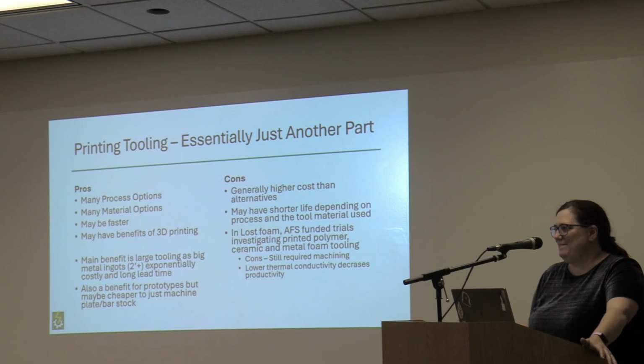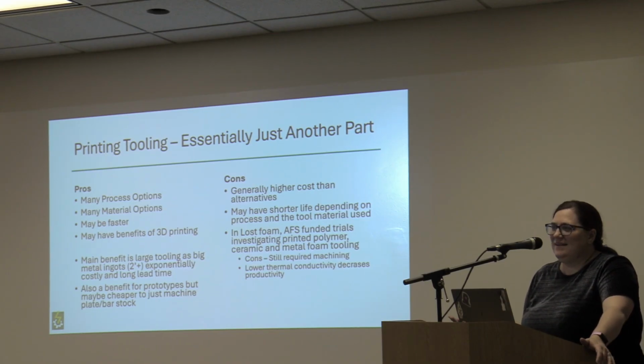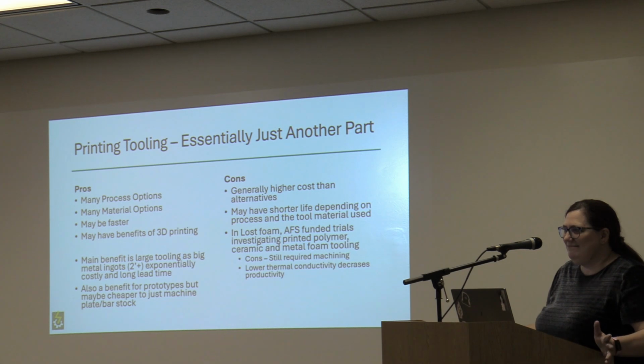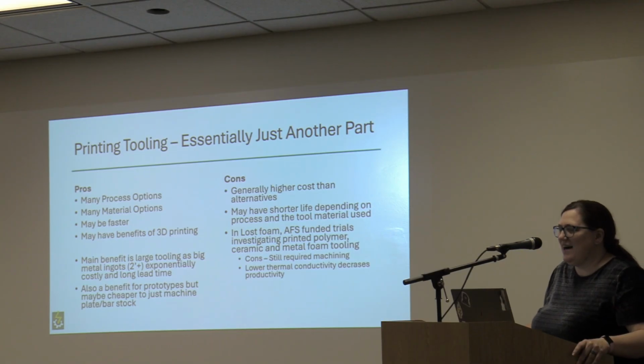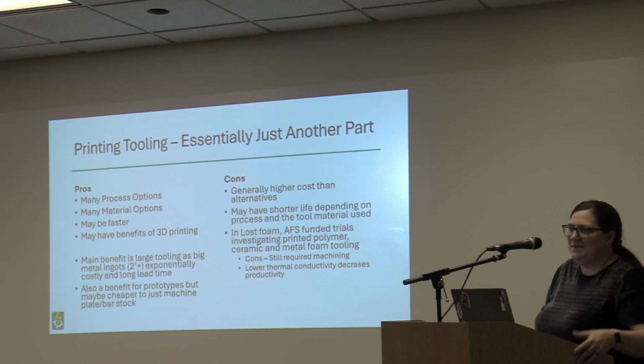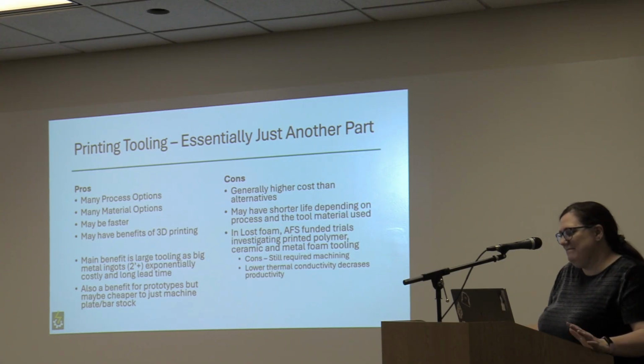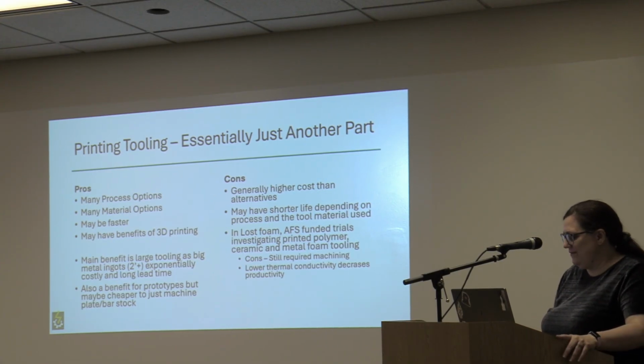Because if you're still going to have to program the CNC machine, you're not saving that much having printed material in the first place. And then the other issue, especially when they tested ceramic and polymer tools, is you can make foam that way, but the thermal conductivity is so much less that you end up taking something that might be a 2 or 3 minute cycle time, and now it's a half an hour cycle time. So that's not very good for productivity. So typically, people are wanting aluminum molds, at least for making foam.